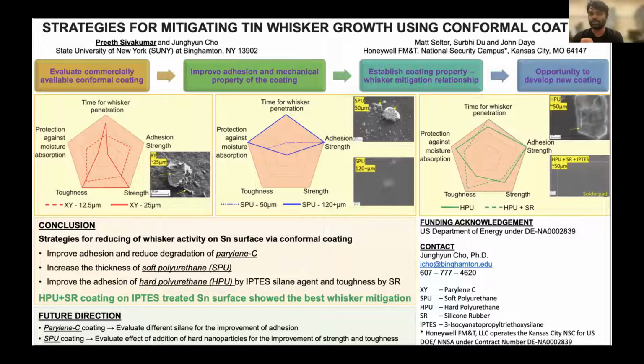So in order to improve the parylene C coating, the adhesion strength of the parylene needs to be improved. And the soft polyurethane, because the material property itself is too soft, the thickness of this coating needs to be increased in order to increase the time for the moisture to reach the tin layer. And for the hard polyurethane, an increase in the adhesion strength and also an increase in the toughness of the coating resulted in delaying the whisker formation. So comparing all the conformal coatings, hard polyurethane with silane agent, which enhances the adhesion strength, and in the presence of silicone rubber, which enhances the toughness of the coating, all of them combined together provided the best whisker mitigation behavior.